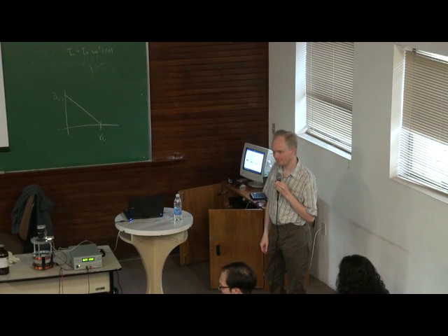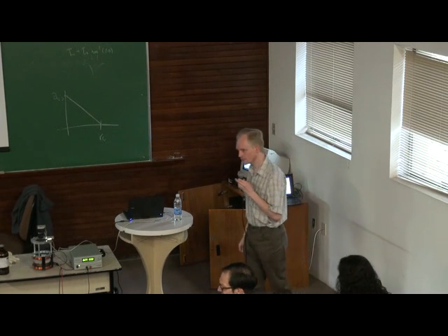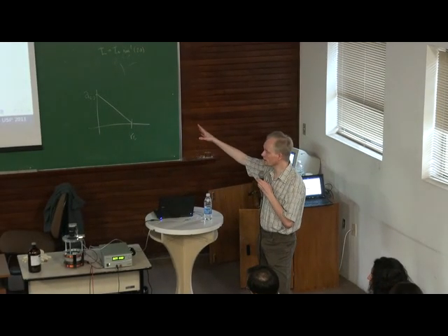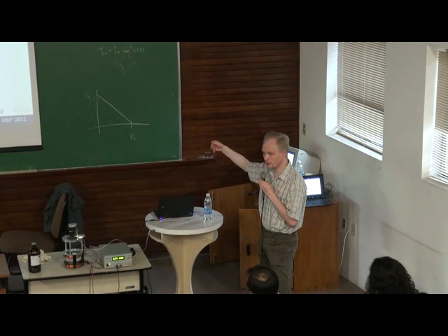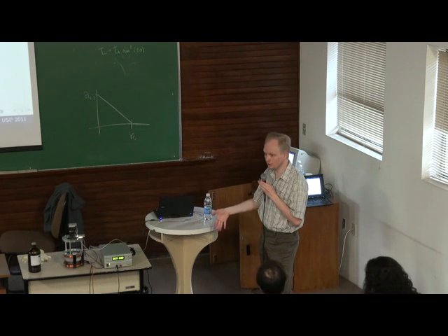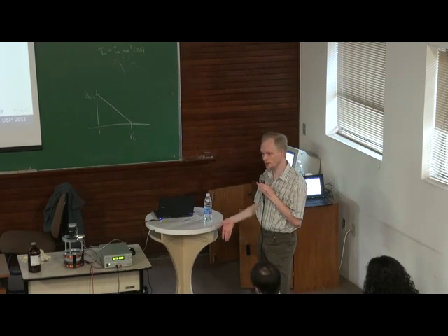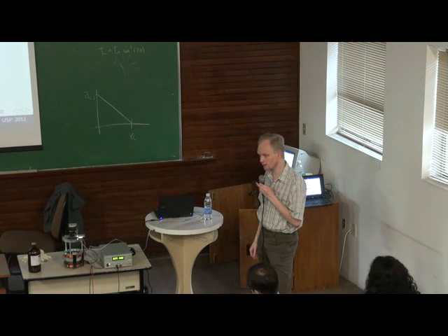And you can get an idea of the critical micelle concentration. Yes. In this simulation, I could just change the density of them and see when micelles start to appear. So I could do exactly the kind of experiment that you would do, changing the concentration. And then looking at the density of micelles, I could look at scattering as a function of concentration and see if suddenly I have the appearance of micelles.